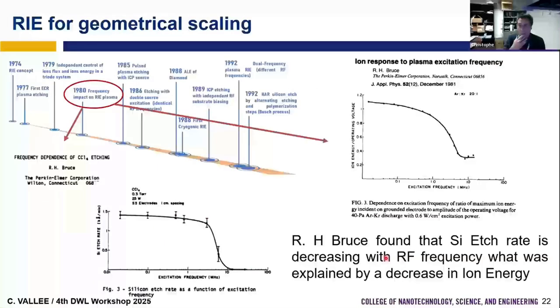Okay, so it's a nice design, but the main issue with the HDP source is that since the plasma is very dense, it can be very difficult to have very energetic ions, because the DC self-bias you will develop is not so high, because you have a high ion flux. So at the same time, the question is, can we still keep the CCP design, but try to have a decoupling with the CCP reactor?